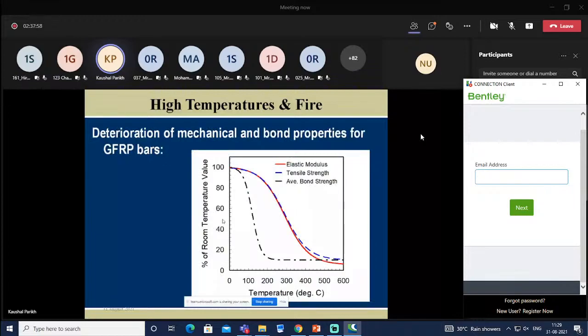And here it has been shown that the red line is the elastic modulus, the blue line is the tensile strength, and black is the average bond strength reduction. It is clearly shown over here. And you just see the dotted line, it is nothing but the critical temperature, where T is greater than Tg. If the temperature reaches beyond this value, all three properties of the FRP, specifically for GFRP reinforcement bars, drastically reduce, and the intentions for which it has to be applied have to be removed. It will become null and void.